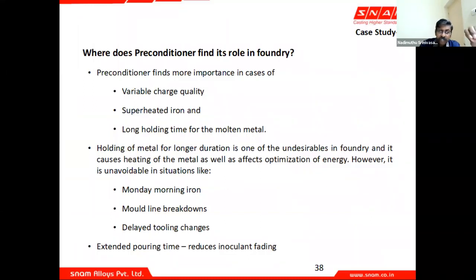So preconditioner is more important in case of variable charge quality, superheated iron, because you raise the temperature and you hold it for long. And typically, when does that happen? When you have a Monday morning, and we don't have it here. Mostly we keep our furnaces running all the while, whereas abroad even the foundries work only 5 days a week. So Friday night or Saturday early morning after the Friday night shift, they shut down the furnace and then they restart, and then they have to raise the temperature. They have to hold it for a longer time, the first melt, before it reaches its melting temperature.